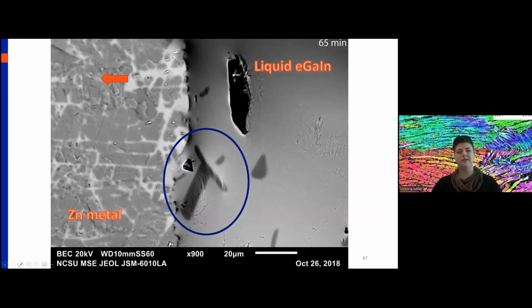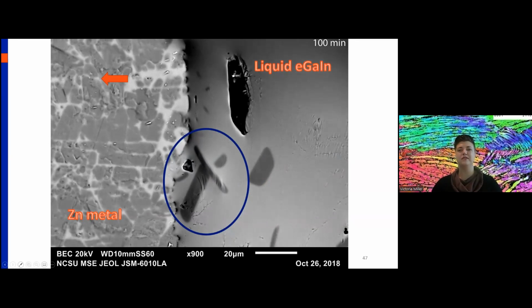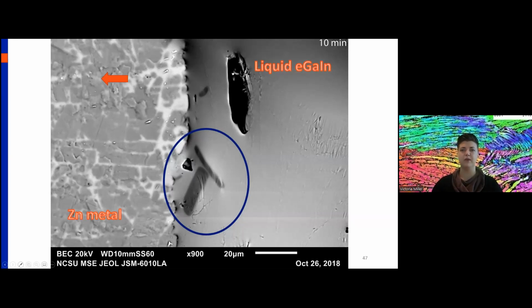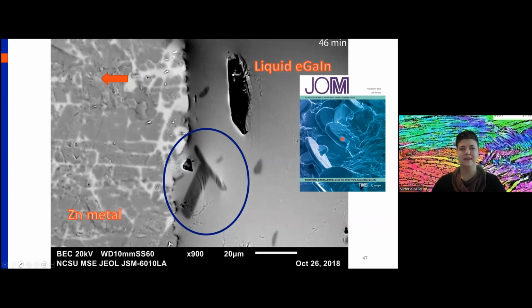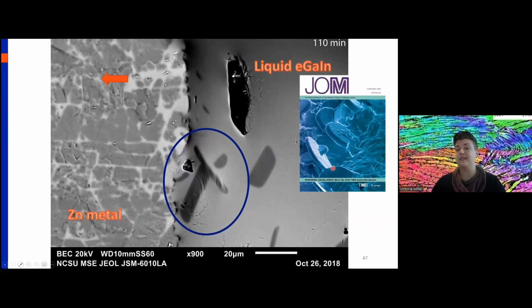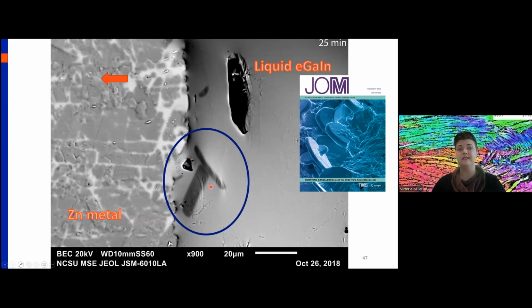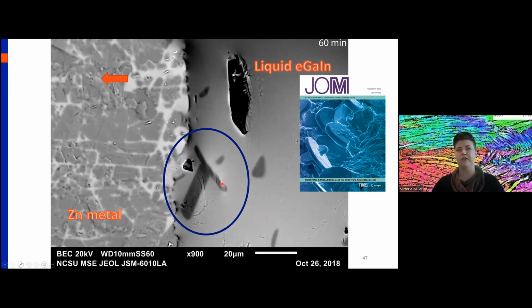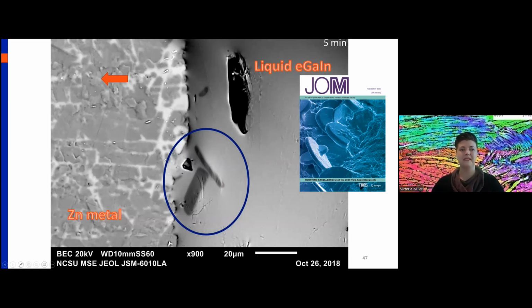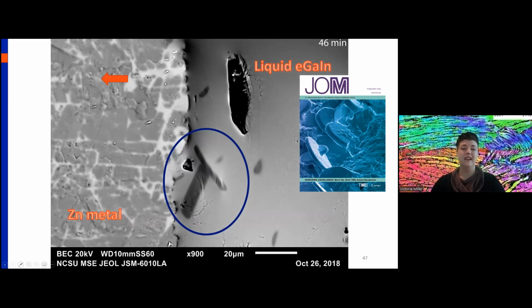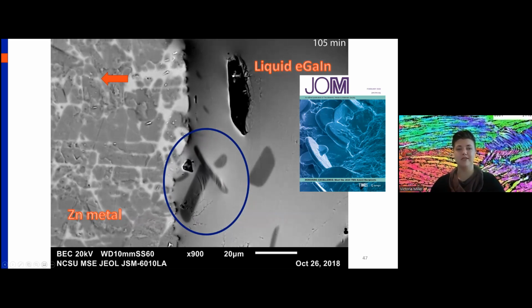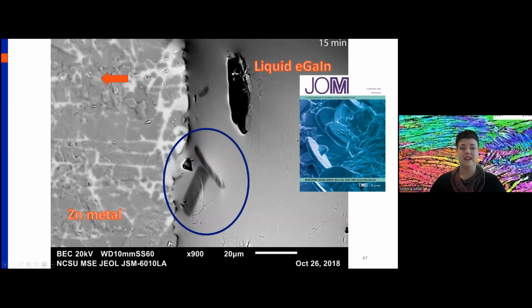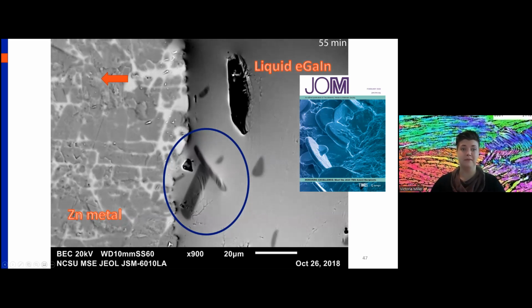So when we exposed a much smaller volume of liquid so that all of the liquid was absorbed, you actually got big platelets of basically pure zinc that were growing. So these growing crystals are large platelets of pure zinc that dissolved into the liquid and then reprecipitated out. So that's very interesting. And unfortunately, I don't have the time to talk about it further right now. Happy to answer questions about it later on, though.